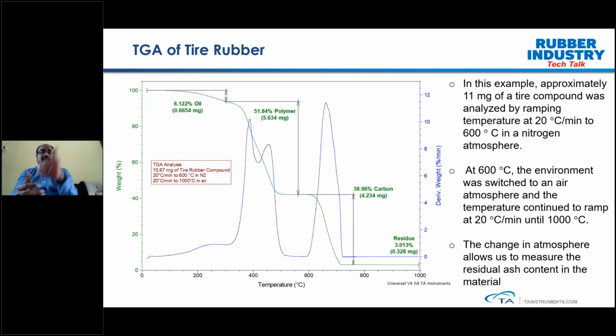So these are some of the key applications, and here I'm going to highlight some of the TGA applications in tire rubber. For example, here you can see a typical standard TGA thermogram where we have taken 11 mg of tire compound and analyzed it in the ramping mode. Generally, it will take 10 to 20 mg of sample put in a TGA crucible. It could be made of either platinum or ceramic, and then we heat it up at a ramp rate of 20 degrees centigrade per minute up to 600 degrees under an inert atmosphere, in this case nitrogen as the inert gas.